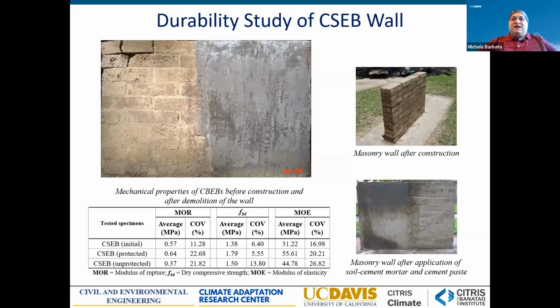Not only that, but actually when we finished our 6 months of testing, we dismantled carefully the blocks from both sides, and we retested them for both flexure and compressive strength. And what we found was that the side that was protected actually ended up being stronger than the initial strength obtained by the blocks before they were put in place.